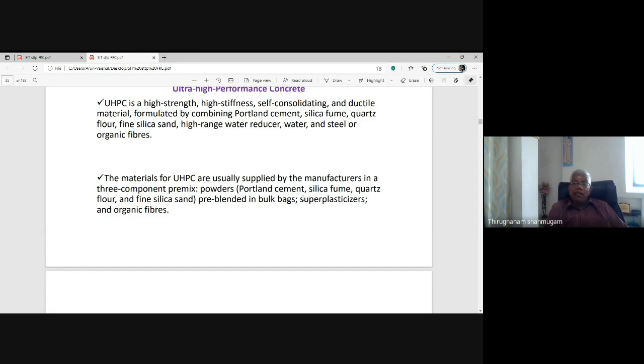In this powder, some siliceous materials and some cementitious materials are used. That is quartz powder, a siliceous material, and the cementitious material, silica fume or microsilica, and fine silica sand as the silica material are added to improve the properties or durability of the concrete. Superplasticizers are added to improve the workability of the concrete, and steel or organic fibers are added to induce ductility.